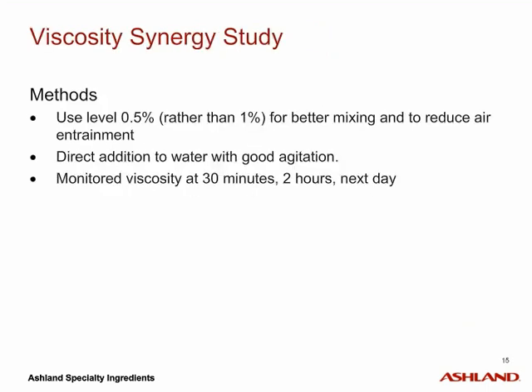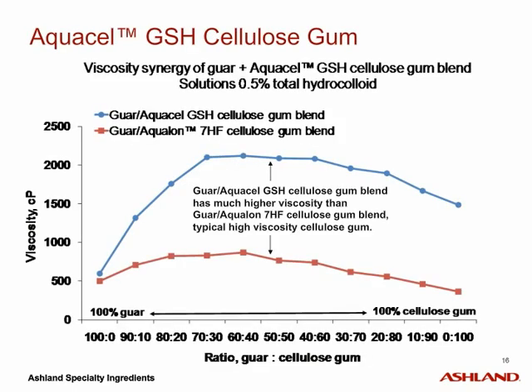Extensive testing took place in our labs to determine optimum use levels and ratios of guar gum to cellulose gum. The total hydrocolloid use level was 0.5% for better mixing and reduced air entrapment. The guar gum and cellulose gum were added directly to water and mixed well. Viscosity was then monitored at 30 minutes, 2 hours, and 24 hours later. The greatest viscosities were seen with Aquacel GSH and guar.